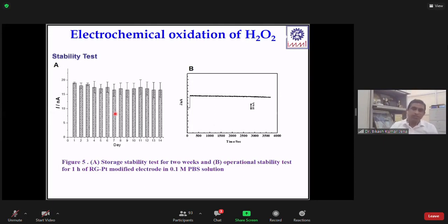So before that, we tried to measure whether this branch platinum and graphene modified electrode is stable or not. If it is not stable, even if we develop a biosensor, it may work for one day, but that will not solve our purpose. So we checked the stability of this electrode towards hydrogen peroxide. We monitored two kinds, one is called storage stability, another is operational stability. Storage means today we have done some measurement, after one day, again we did the measurement. Like that, we observed that it is working up to 14 days. And the same electrode you can use every day. That means, as a disposable kind of electrode, you can use it 14 times. And operationally, we ran it continuously for more than 1 hour and it is working. So the storage and operational stability of this electrode is quite good.